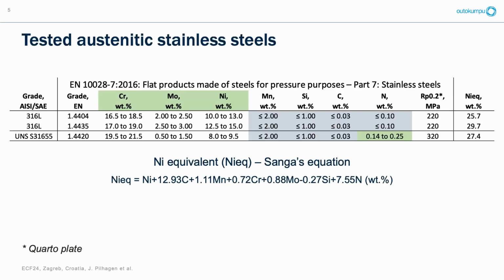And then we also have another grade, 4420, which you can call a lean 316 grade. The idea here is to make it more cost-effective by reducing the molybdenum and nickel, which are the most costly elements. So here we have an increased chromium content to compensate for the molybdenum, and an increased nitrogen to compensate for the lower nickel. And by using nitrogen as an alloy addition, you also get a higher strength in the material, as you can see in this plot.